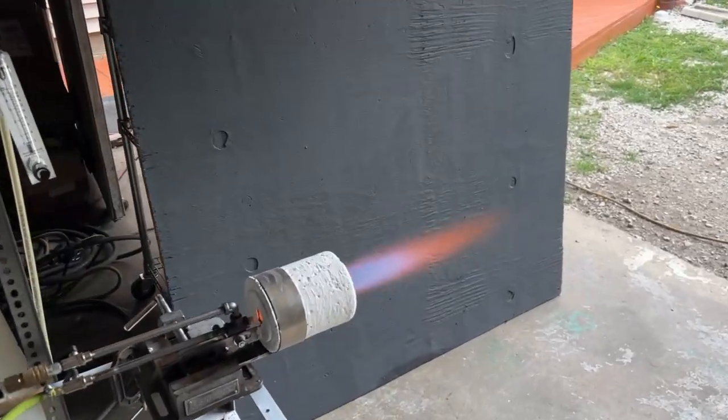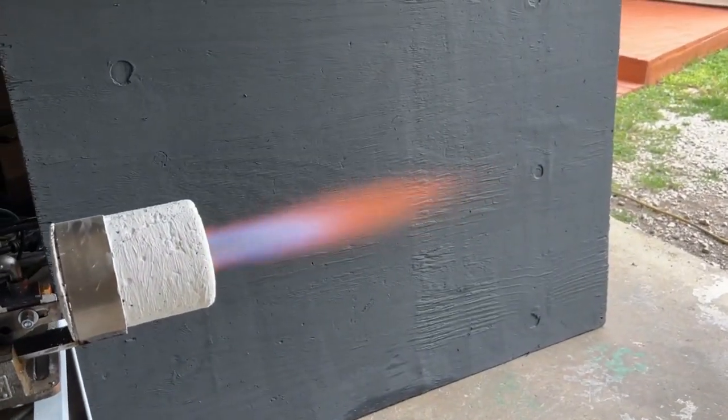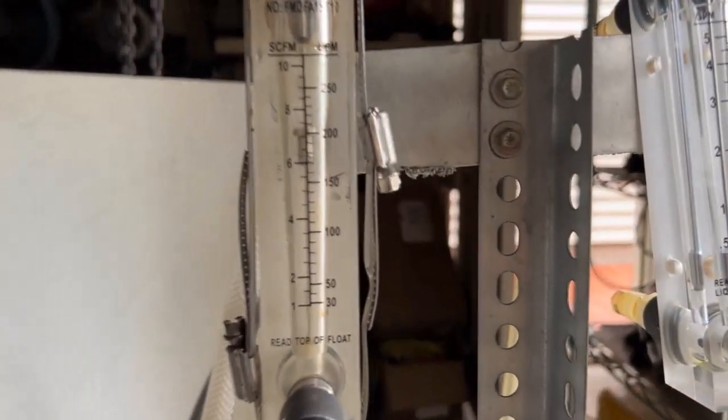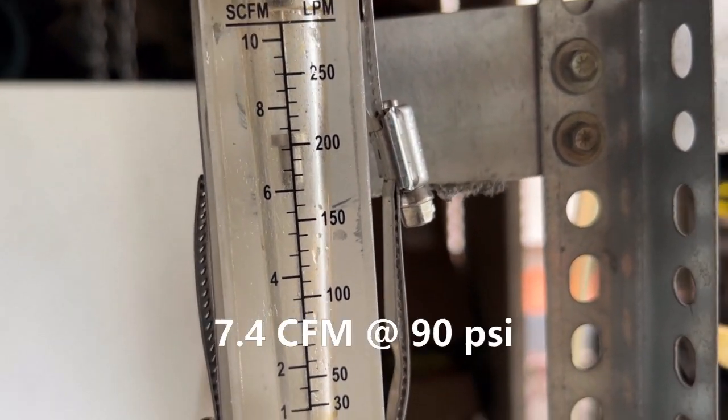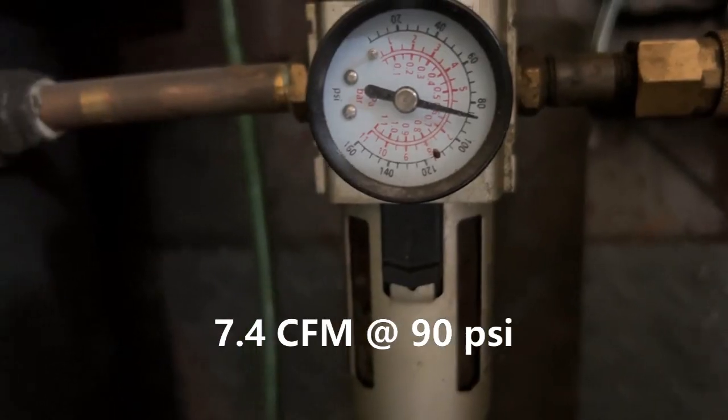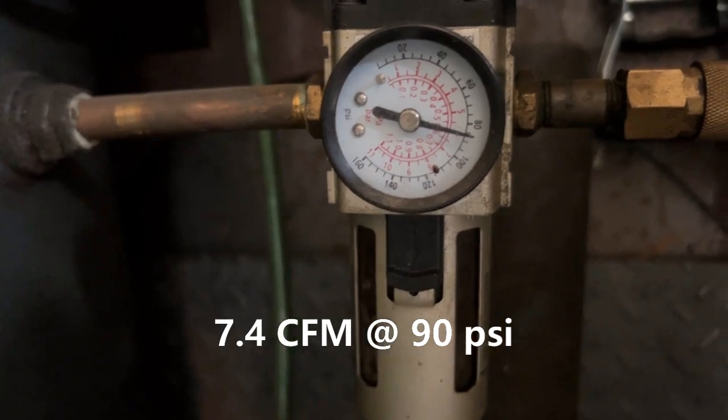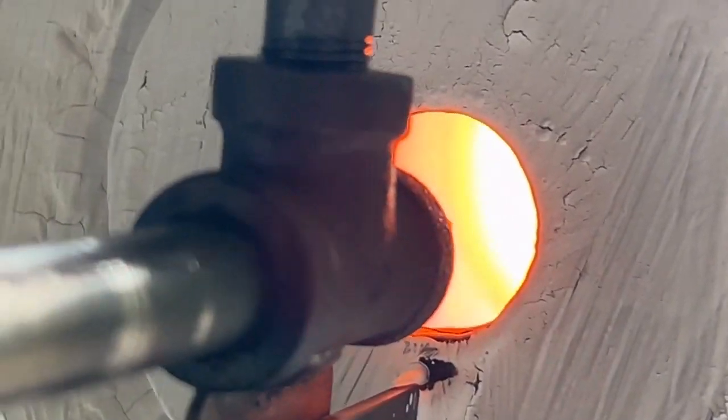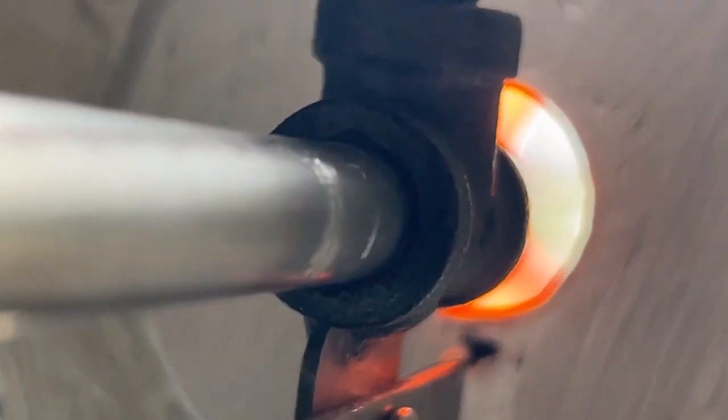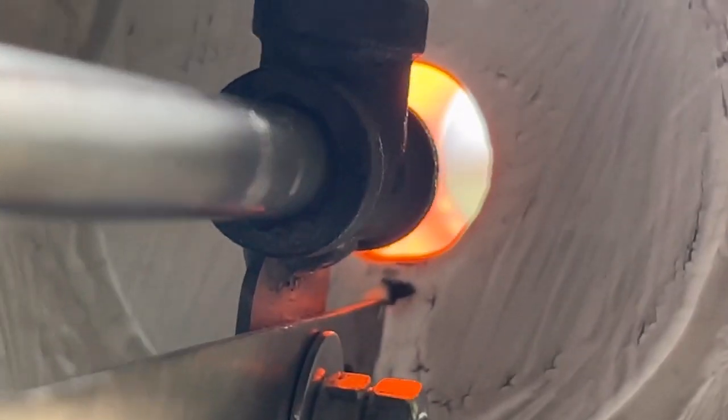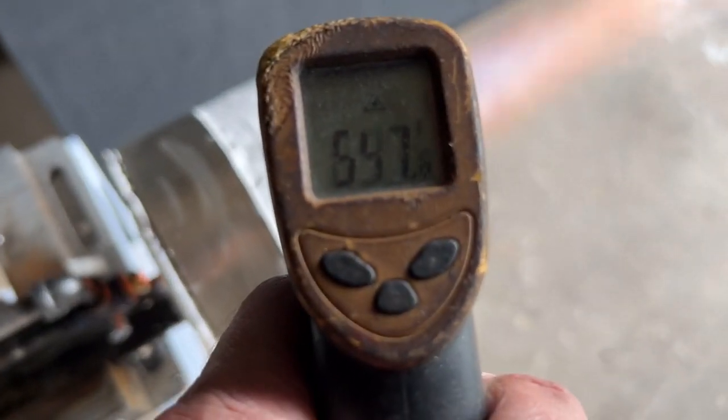Okay, this next little bit of footage exhibits precisely why we need to have some type of water mitigation. I have two water traps on this system and look at the amount of water still flying through. So a desiccant charge is absolutely essential if you're doing anything that requires extremely high temperatures, anything above like 2600 degrees Fahrenheit.